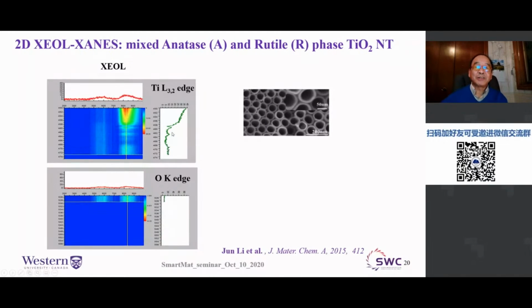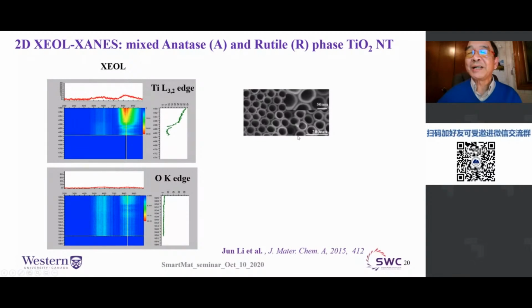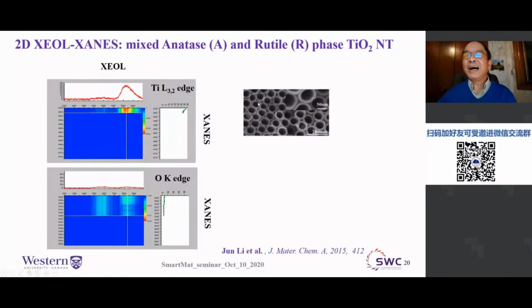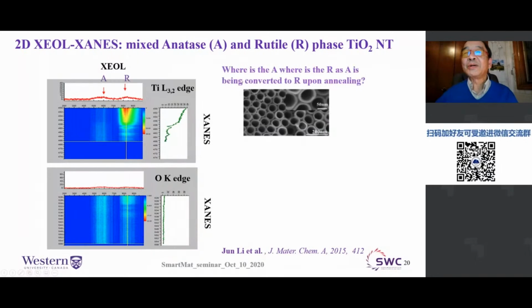In fact, we can track the optical response as it scans across the edge, right? And in this particular titanium oxide nanotube, we are asking the following question, because we started with anatase, and by annealing it, it becomes rutile. But we truncate the annealing process, so what we get is a mixed phase. So then the question, in a mixed phase, where's the rutile? Where's the anatase? And how does the phase transition take place? And we can get information by analyzing this in great detail, right?